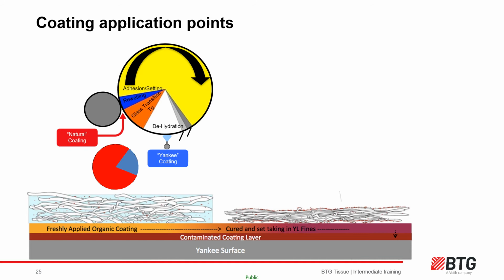The red dots are the fines, fibres, fibrils, colloidal material and other contamination which will have cycled up in the backwater and become presented at the nip. We can also see the various coating layers which we have discussed in previous slides. As the sheet dries around the Yankee, the water is evaporated, but the contaminants are left behind. They can't go anywhere else when the drying is exclusively evaporative.